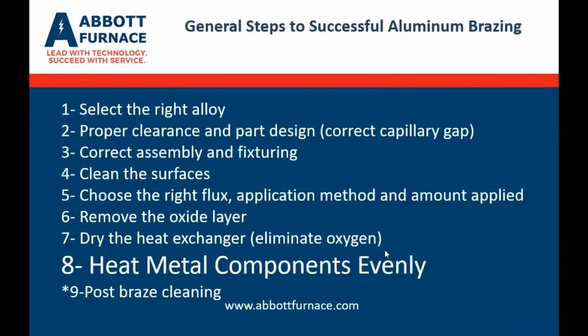So what are the successful steps for aluminum brazing? As far as generally, select the right alloy. You have to have the right clearance in part design, as far as capillary gap, the correct assembly and fixturing, clean part with the right flux and application method and the right amount of flux applied. Then you remove the oxide layer off the part. Remember, oxygen is a major enemy of the process. Drying the heat exchanger prior to going into the furnace, which eliminates oxygen.